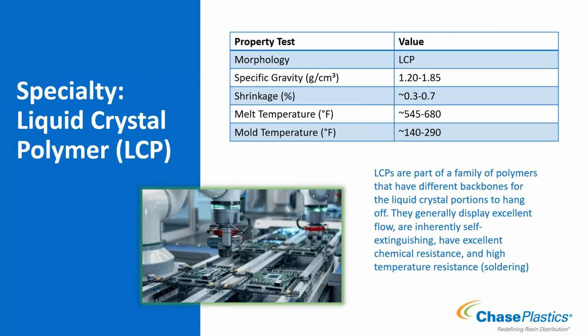You'll notice there's a lot of ranges here. The reason for that is LCP is more of a family of polymers versus one distinct chemistry. You can utilize different backbones that the LCP sections are grafted off of, and because of that you'll get a varying range of performances for LCP. You'll see specific gravity ranges from 1.2 to 1.8. Your shrinkage is lower for these materials, typically a lower shrinkage from them. Your heat can be anywhere from mid fives up to almost 700, again depending on the backbone being used, because that will help dictate how you're going to process it. And your mold temperatures from mid 100s to almost 300 degrees, again depending on the backbone.